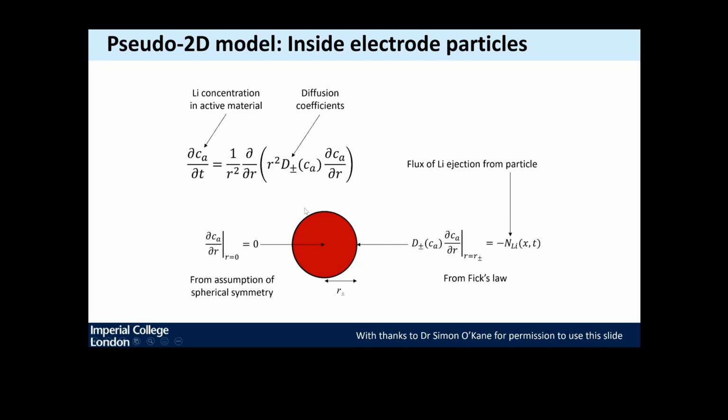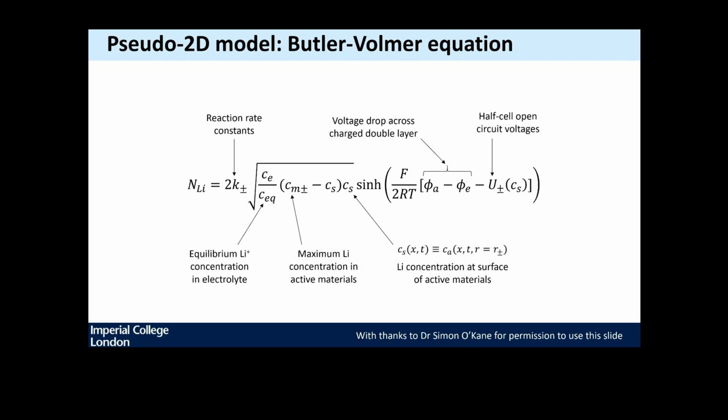And it's going to be at the surface of this sphere that I'm going to allow the Butler-Volmer, those Faradaic reactions to happen in order for electrons to be transferred in and out of the circuit. So this is what the Butler-Volmer that I showed you before looks like for batteries after a few assumptions. But basically it's the same, it's the two exponentials.